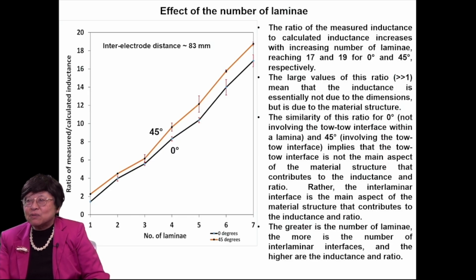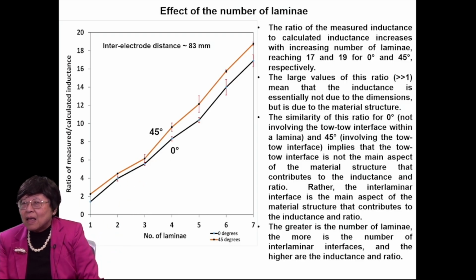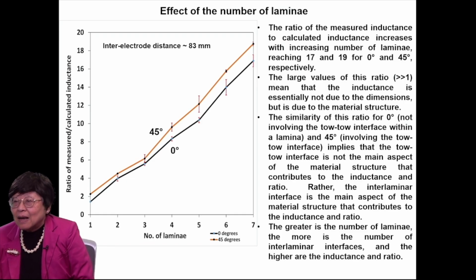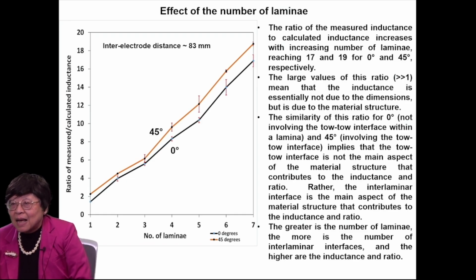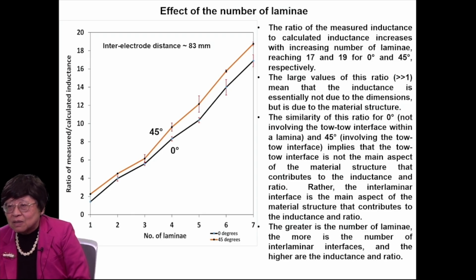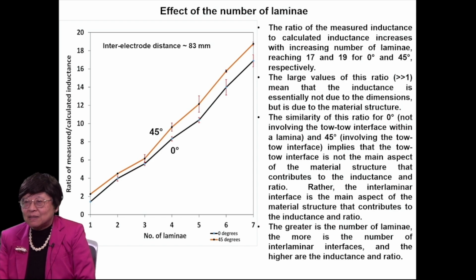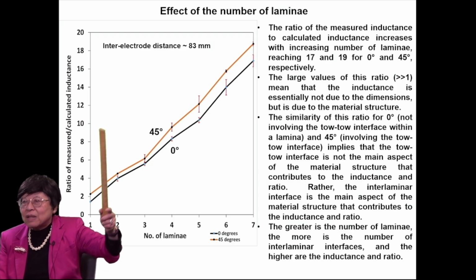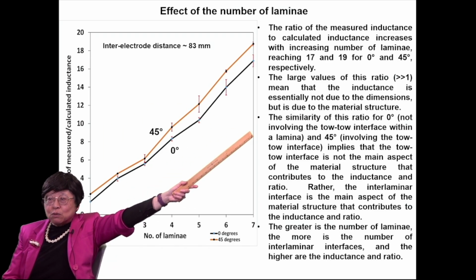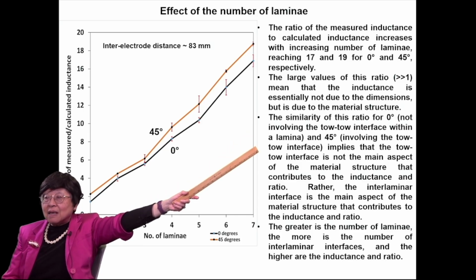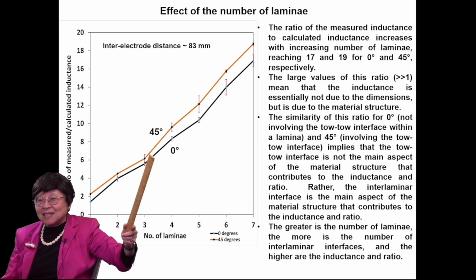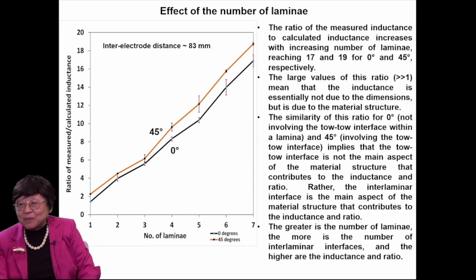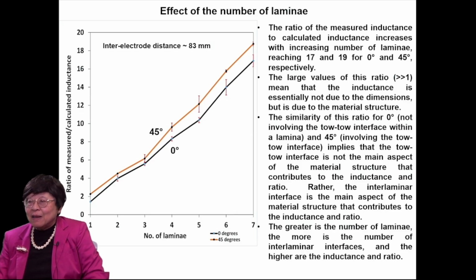And the similarity of this ratio for the 0 and 45-degree cases indicates that the tow-tow interface is not the main aspect of the material structure that contributes to the inductance and this ratio. Rather, it's the interlaminar interface that's the main aspect of the material structure that contributes to the inductance and this ratio. Note that the 0 degree does not involve tow-tow interface, whereas the 45 degrees involve the tow-tow interface. Yet, they have similarity in the ratio. Okay? And this is why I said that the interlaminar interface is the main aspect of the material structure that contributes to the inductance and the ratio.